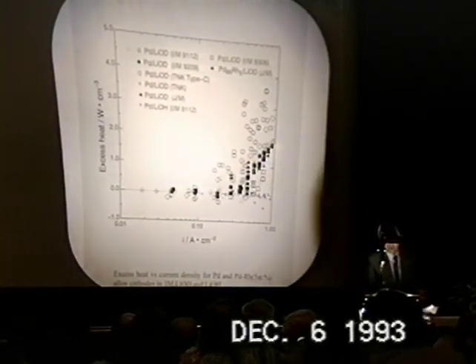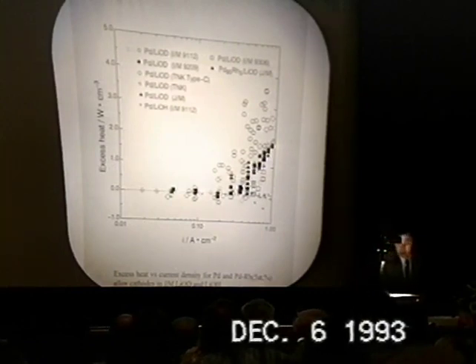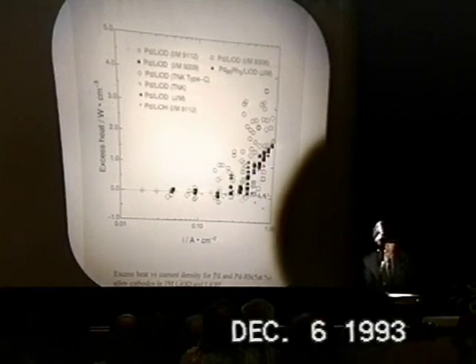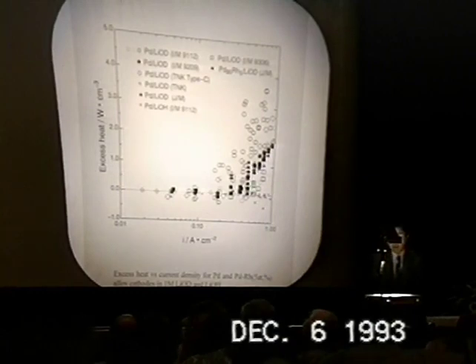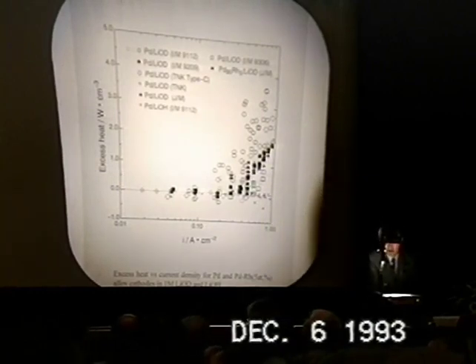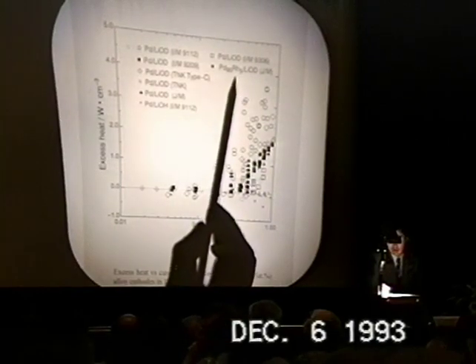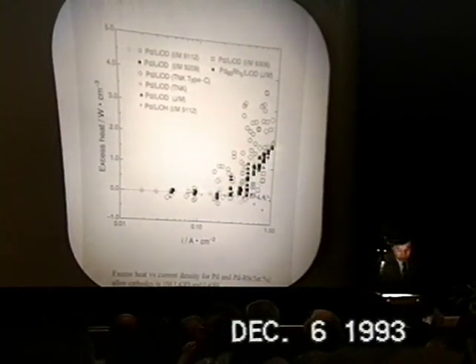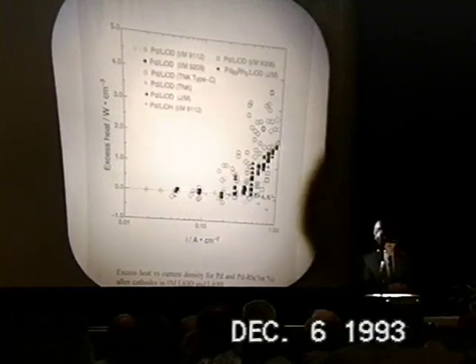And the same data as a function of current density is much more systematic. We haven't tried to plot all the data as a function of cathode overvoltage, because the data for the cathode overvoltage are still not available for this 5% loading palladium alloy electrode. So these are all we have got up to this point.